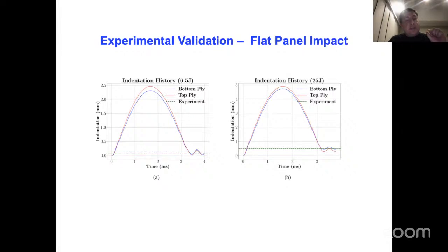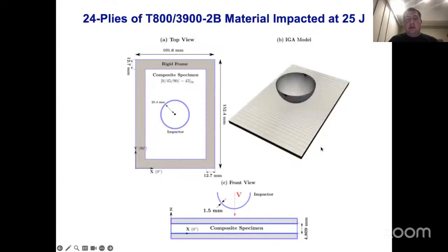So that's the plasticity effect. We're actually able to capture not just the force histories, but the size of the dent, because of the plastic formulation. And then the same thing for the 25 joule case. Much higher displacements. They come back at the end of the impact and again oscillate around an experimentally measured 0.5 millimeter dent on that plate.